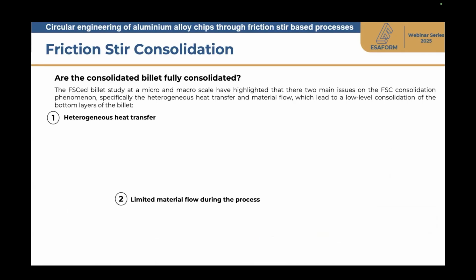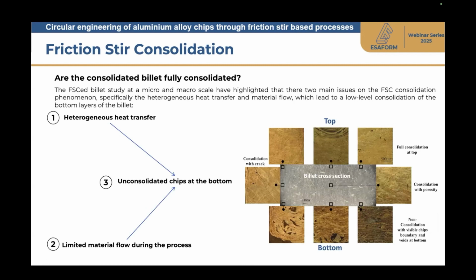It should be observed in particular that if we consider locally what happens in terms of consolidation in different parts of the transverse section of the billet, the combination of the heterogeneous heat transfer and the limited material flow during the process leads to some defects, especially at the bottom of the billet. So we observe all along the transverse section of the billet an unconsolidated portion of chips at the bottom of the billet. So the process engineering has to be aimed at the limitation of such zone of imperfect bonding condition of the material in the final billet we will obtain.